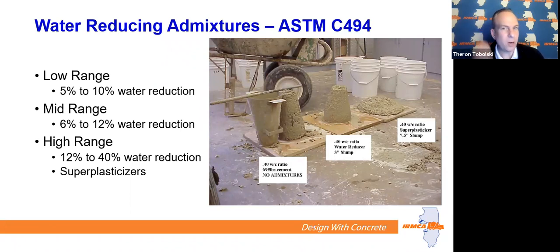And if you can see here in this picture, first you have a 0.4 water cement ratio concrete with no water reducer. There's 695 pounds of cement. You can see that when they did a slump test on it, the concrete didn't even fall. There's really no slump there. It's a 0 or ½ inch slump.